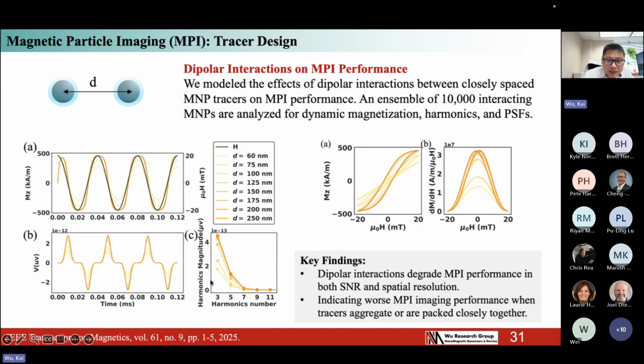And you can see from the harmonic signal, and also the time domain response of particles. With the dipolar interaction included, the response of the particle is weaker compared to no dipolar interaction, with the darker orange color for no dipolar interaction, and lighter color for high dipolar interaction. The dipolar interaction will reduce the response of particles under the magnetic field. It will also reduce the MPI signal intensity, which indicates that if the particles are aggregating in the tumor region, the signal is expected to lower down due to the dipolar interactions.